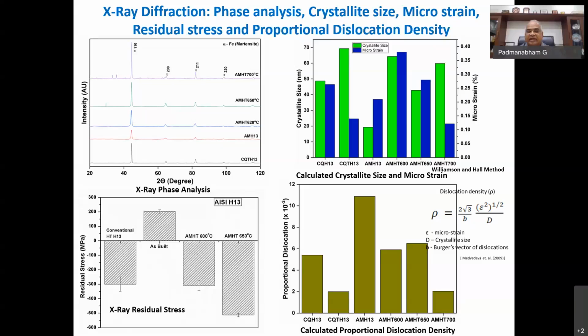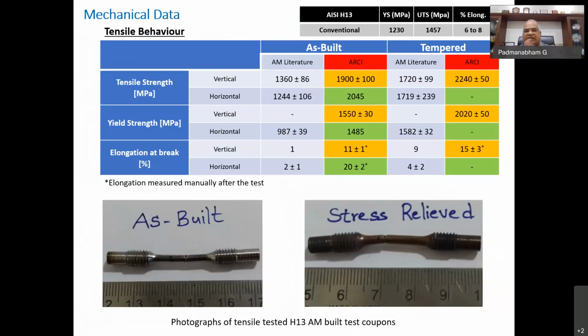And you can clearly see that AM H13 has got the highest dislocation density, which impedes the motion of dislocations and then gives the higher properties that you're looking for. So AM is a beneficial process for this kind of steel. That is clearly reflected in the properties you're getting from the AM-built H13 tool steels.